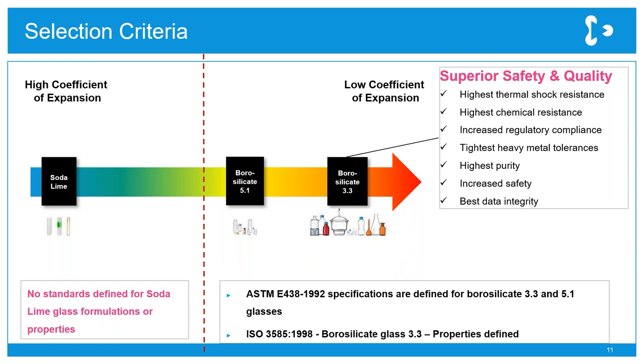There are no standards in place for soda lime glass as well. And that means there's no standardization around properties, so it's very much potluck with what the exact composition of a soda lime product is. But in contrast, borosilicate products are typically highly regulated and they do have an ASTM standard. 3.3 also has an ISO standard, so all manufacturers of these products must conform to these guidelines, so it's very tightly controlled. Borosilicate 3.3 is regarded as a very safe material as it has a low coefficient of expansion, and it's been tried and tested for a long time in the pharma industry. It's tightly controlled and we can rely more on the purity of 3.3. For example, if we need to ensure there's no heavy metals present.